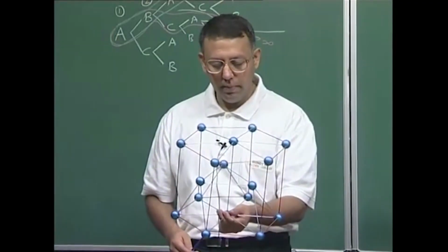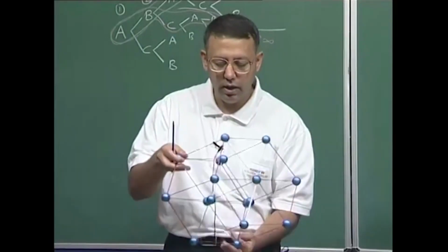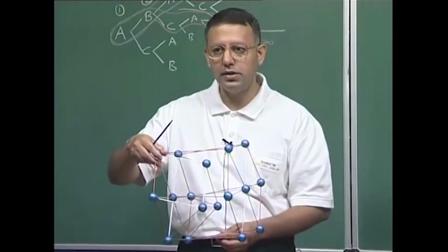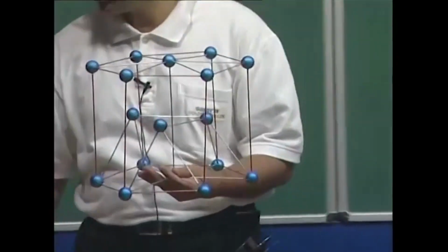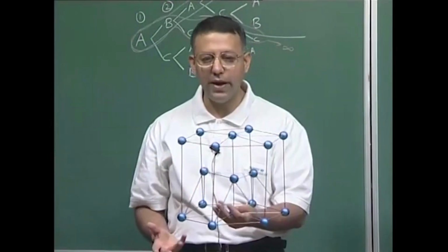Now, as I mentioned, this kind of a structure, let me show from the side, has approximately the ideal c/a ratio. But as I told you, real hexagonal close packed crystals can have a c/a ratio which is extended, that means it could be larger or smaller, and that means that my hard sphere model of atoms is no longer valid.